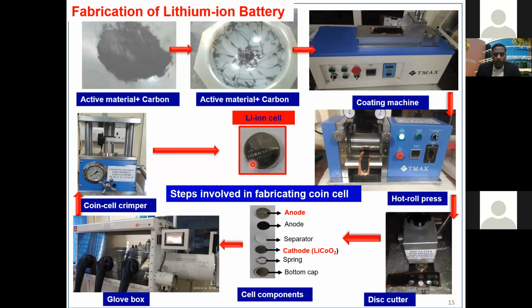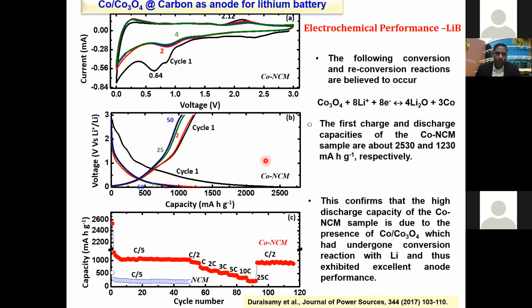And this is the finished lithium-ion battery. What is the performance? The performance you can understand using these 3 parameters. You run the cyclic voltammogram; the appearance of the redox peaks confirms that lithium is reacting with the cobalt oxide this way. Thereby, cobalt oxide is converted into cobalt and back and forth.